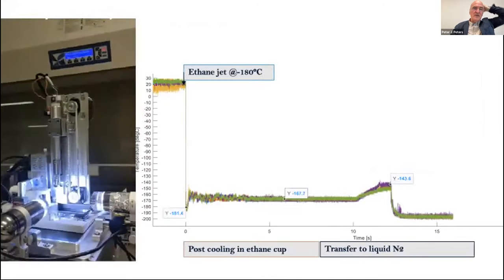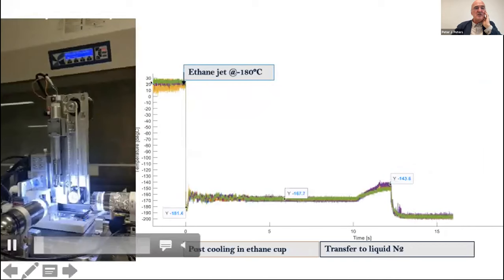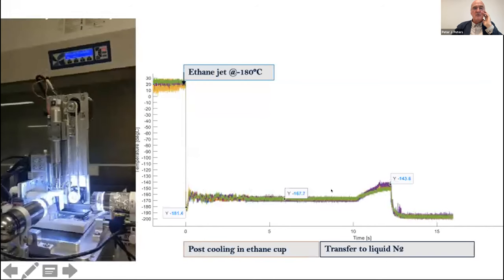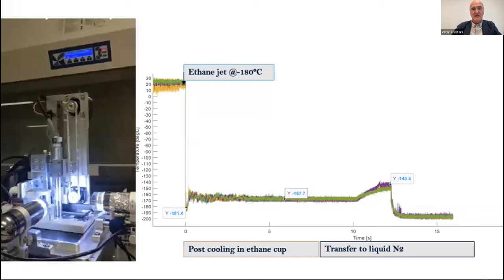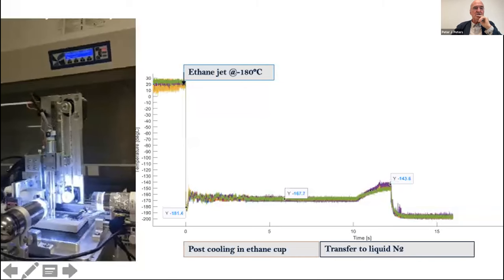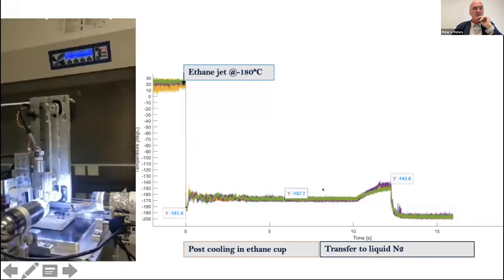So here you can see what we have at the moment. We start with 20 degrees Celsius, and then we go down. That is a very rapid vitrification. Then we keep it at very low temperature, so that we don't get into cubic ice or ice crystals. Then we store it in liquid nitrogen at the end. It took a long time before we were able to achieve this, but now with all kinds of insulation, we have it up and running very nicely.